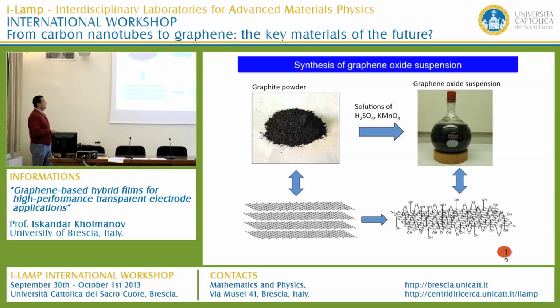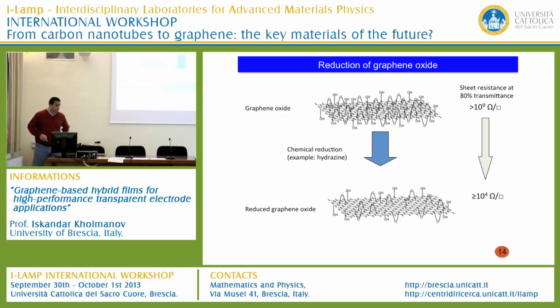It contains a lot of functional groups attached to these individual graphene platelets. The graphene oxide itself is not conductive. It has a very high sheet resistance. For transparent conductive applications, we need to reduce graphene oxide. We need to remove the oxygen-containing functional groups, and in this way we can obtain reduced graphene oxide and significantly decrease the sheet resistance of the reduced graphene oxide.